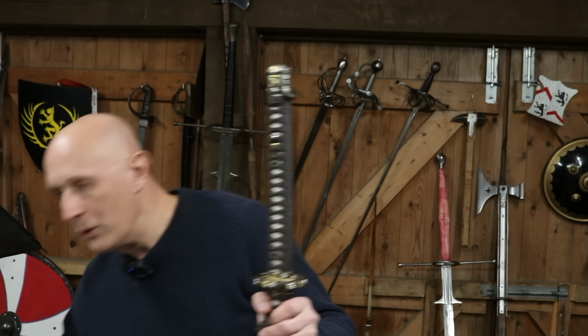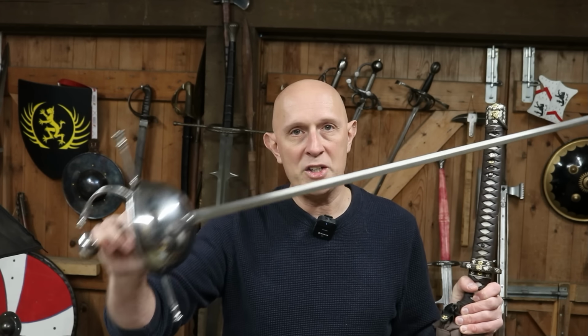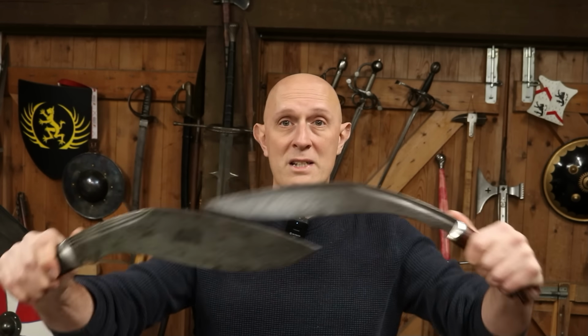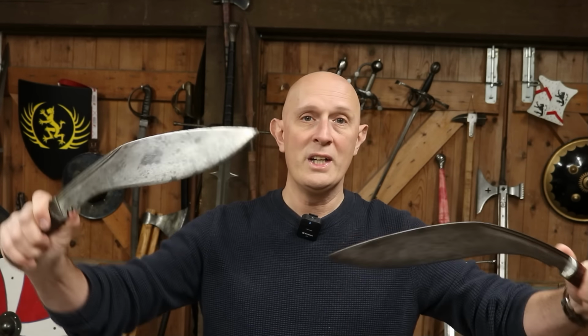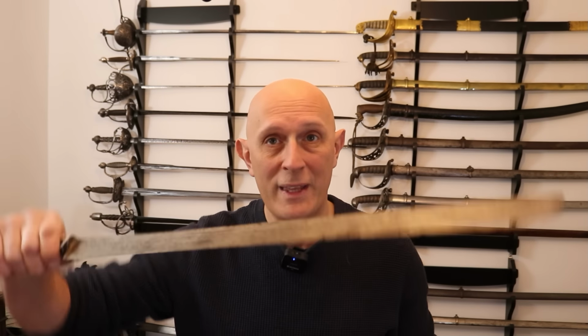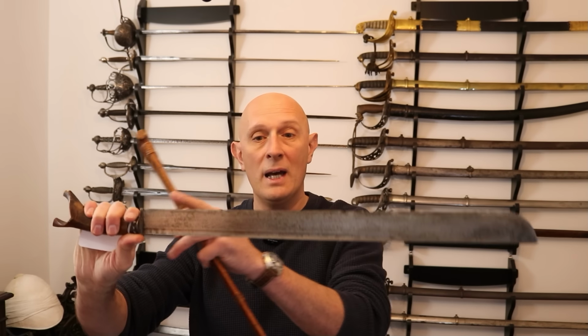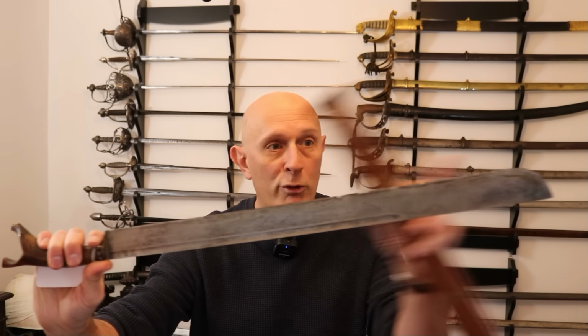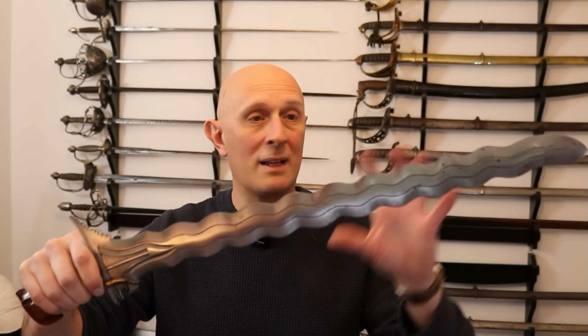But if you only edge quench something, then you can't create a spring from that blade in the way that you do when you through quench, when you entirely quench a blade, for example, on this rapier. Other weapons which include edge quenching, for example, are kukris. These are usually edge quenched with water along the edge, but they're not usually quenched on the entire blade. In fact, edge quenching was completely normal all across Asia, and we find it on all sorts of Southeast Asian weapons, which very often have a soft back and a differentially hardened edge at the front only. And we also find the same thing, for example, in the Philippines, where things like this kris are usually edge-hardened, but not hardened all the way through.